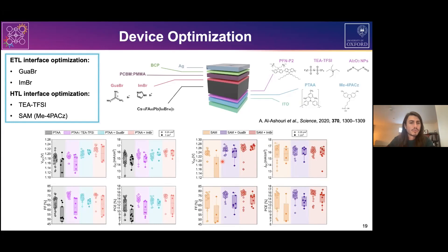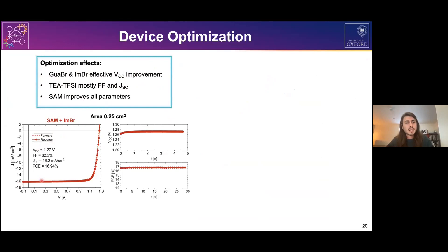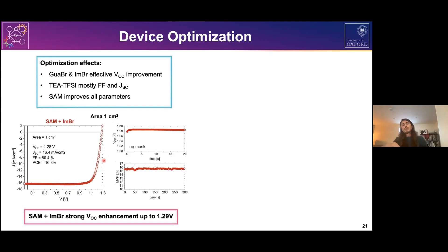From this combination of improvements: guanidinium bromide effectively improves VOC, TEA-TFSI mostly improves fill factor and JSC, and the SAM pushes up all parameters simultaneously. Combining the best HTL improvement with the best ETL improvement gives record devices with stabilized PCE around 17%, fill factor above 82%, and very high open-circuit voltages. Notably, moving from small-area to large-area devices, we could maintain almost all the same parameters — fill factor above 80%, PCE around 17%, and VOC of 1.29 V.